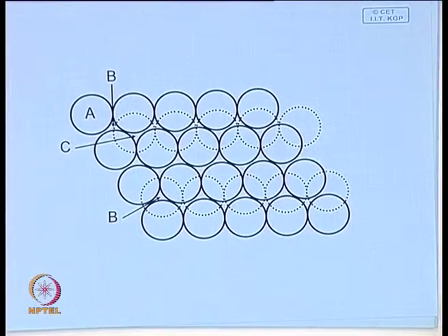But we found out that the energy of this type of perfect dislocation is more than that of partials, and we also showed you with a hard sphere model that it is much easier to move with the help of partial displacement or partial displacement vector. In fact, what we said is in a face centered cubic crystal, the different layers are arranged in the fashion which is shown over here.